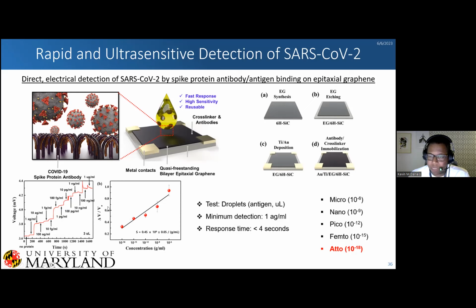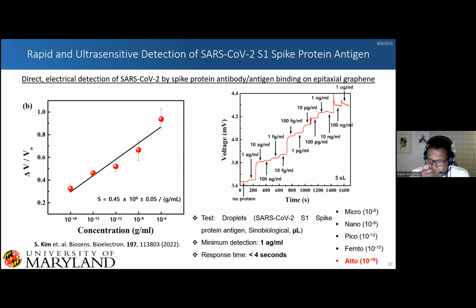And so our limit of detection really is a single copy to less than a single copy of SARS-CoV-2. And we're able to go down from the 10 to the minus 18 gram attogram range all the way to a microgram. And so really we're spanning 12 orders of magnitude in detection range with this sensor. And the response time is super, super fast. Generally less than 4 seconds, we get a response. Most of the time we get a response in less than a second. And so, as I said, we're getting down to an attogram range.